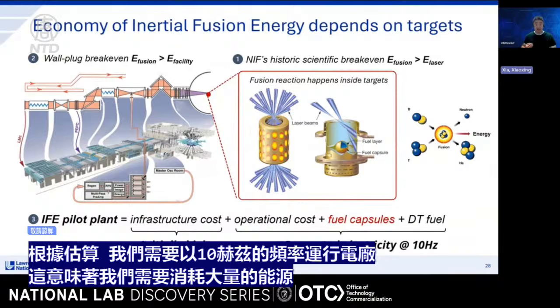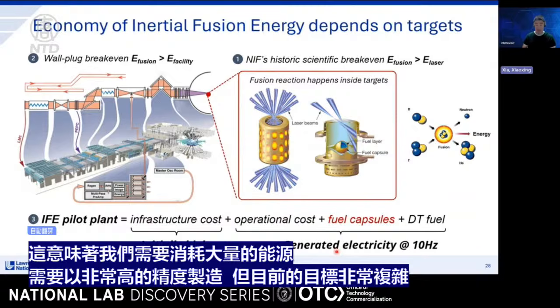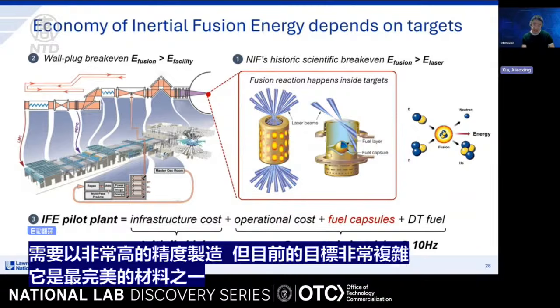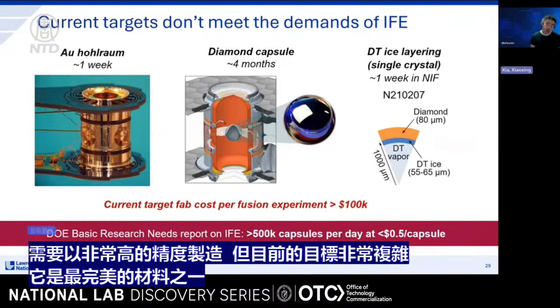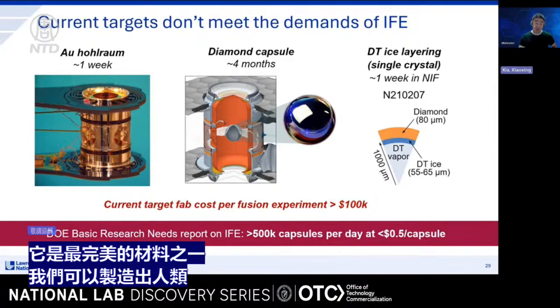That means we need to consume a lot of targets that need to be manufactured with very high precision. Today, the target is very intricate. It's one of the most perfect materials we can make by human hands. We start from a gold hohlraum that takes about a week to machine. And on the inside of the hohlraum, there's a capsule made of diamond that needs to be polished to perfection.